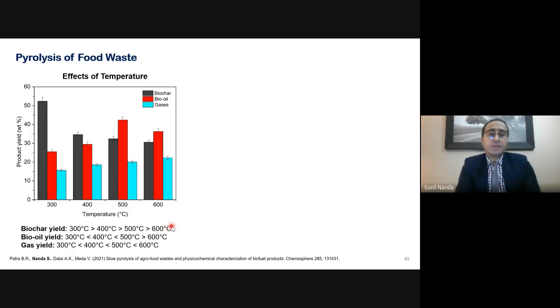In this study, we took food waste that we collected from a local restaurant, and then we pyrolyzed it at different temperatures. So what we noticed here is that when we increase the temperature, the biochar yield tends to decrease. Because if you remember, I mentioned that pyrolysis results in biochar, bio oil, and gases. Now, these are the three different products, and these are the mass distributions.